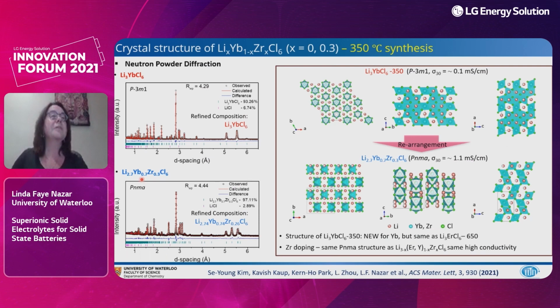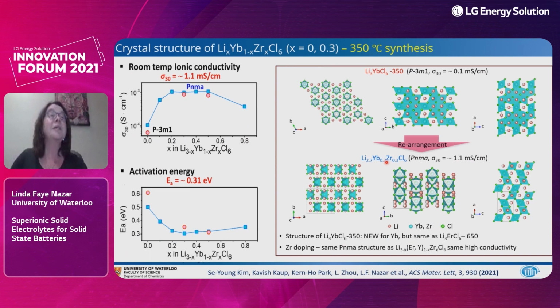This just shows the effects of, again, increasing or substituting these materials with zirconium. So the story is really very similar to what I showed you for erbium and yttrium, just slightly different pictures, slightly different structures, but the material that we obtain on substitution is almost identical for the erbium and the yttrium. And we see a similar decrease in activation energy and increase in conductivity. So this is all quite comforting.